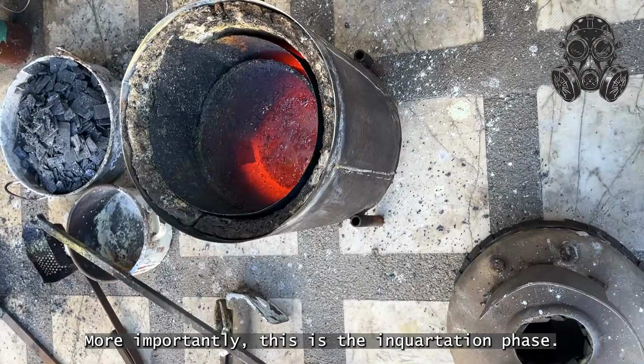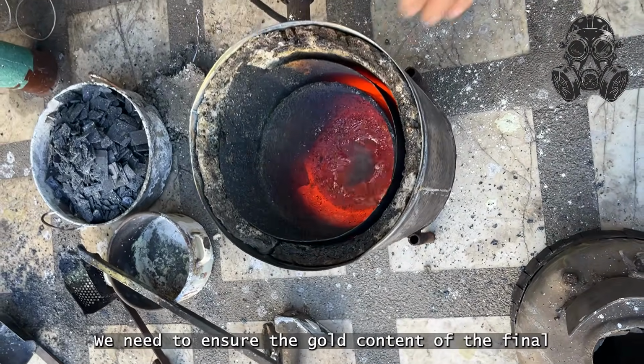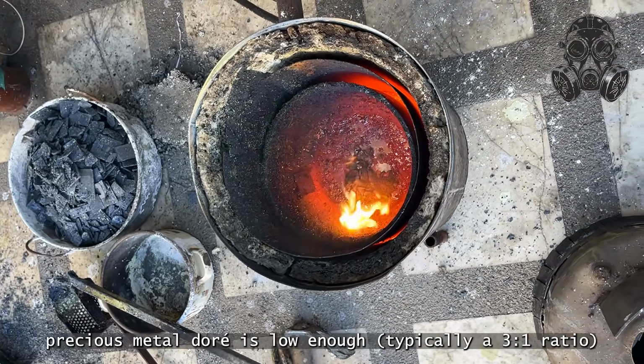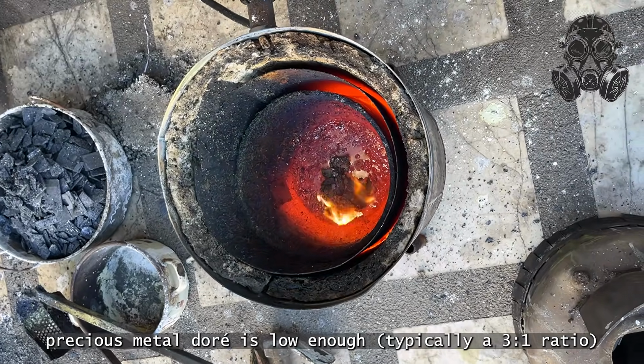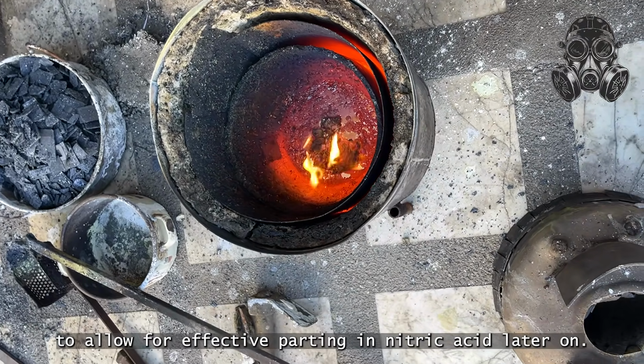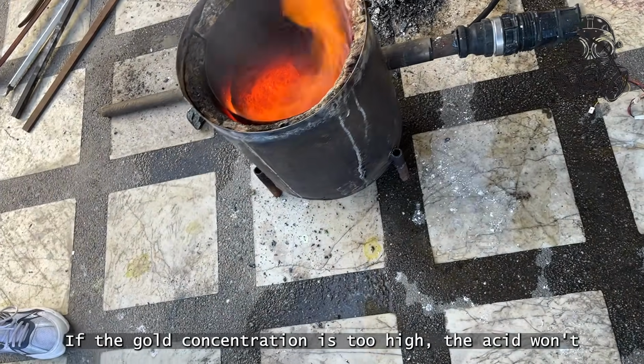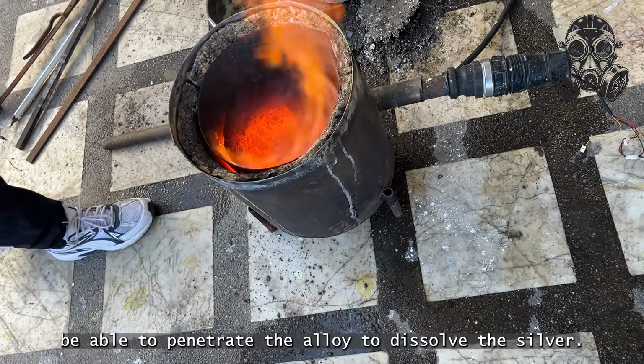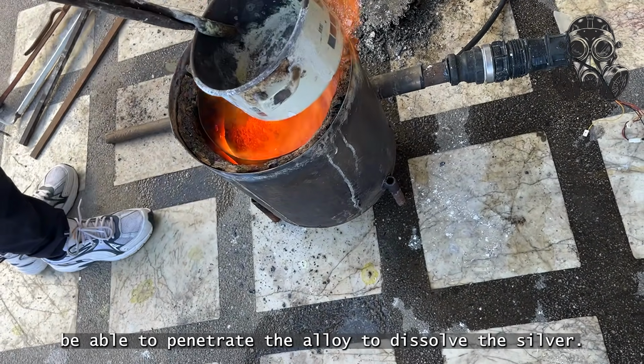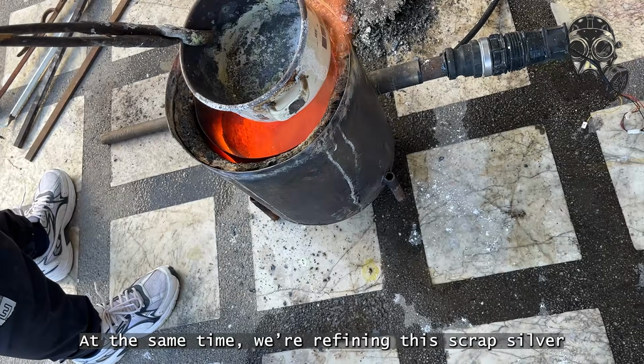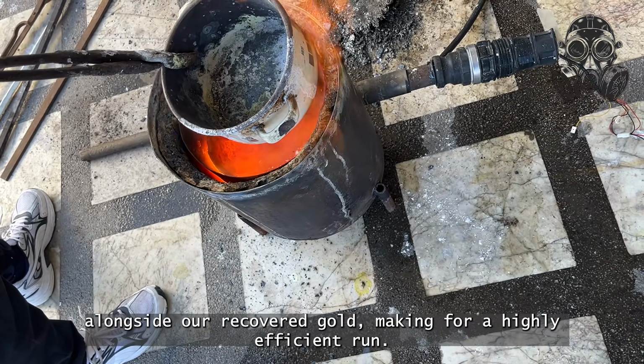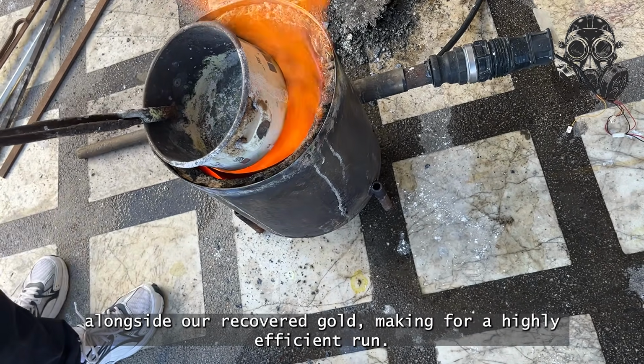More importantly, this is the inquartation phase. We need to ensure the gold content of the final precious metal doré is low enough, typically a 3:1 ratio, to allow for effective parting in nitric acid later on. If the gold concentration is too high, the acid won't be able to penetrate the alloy to dissolve the silver. At the same time, we're refining this scrap silver alongside our recovered gold, making for a highly efficient run.